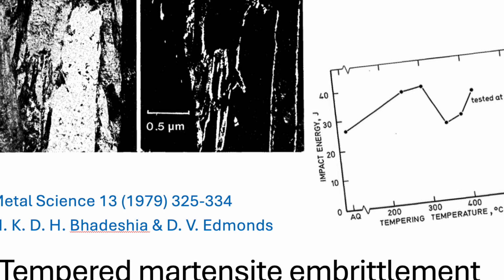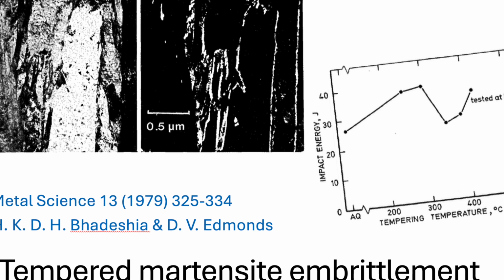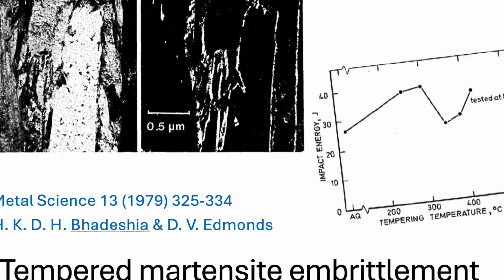So they decided to look closer, really zoom in on the structure itself, specifically at the lath structure. Okay, we're immediately hitting some jargon there. When you talk about the lath structure, what are we actually visualizing inside the metal? Good question. When you quench steel very rapidly, it transforms into a phase called martensite. But this martensite isn't just one solid block. It's made up of extremely fine, almost needle-like features. We call them laths. Think of it like a huge bundle of microscopic needles packed incredibly tightly together, and where these tiny needles meet, you have boundaries. Got it. Almost like a dense fiber composite, but it's all steel. Sort of, yeah. That's a decent analogy.